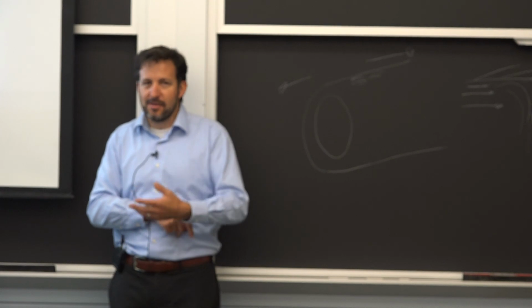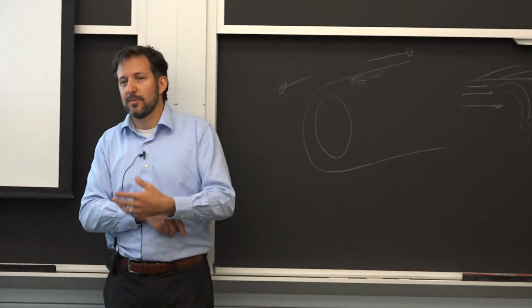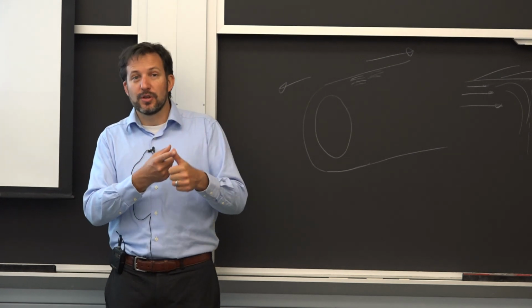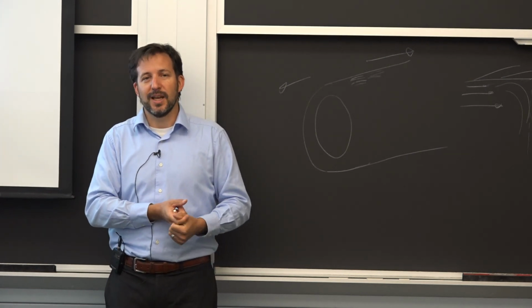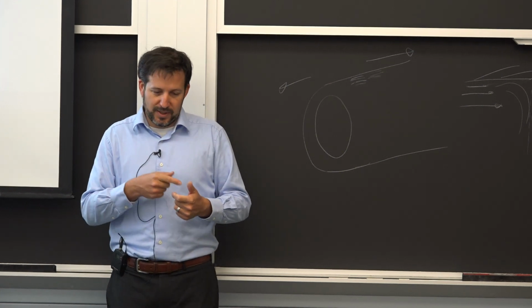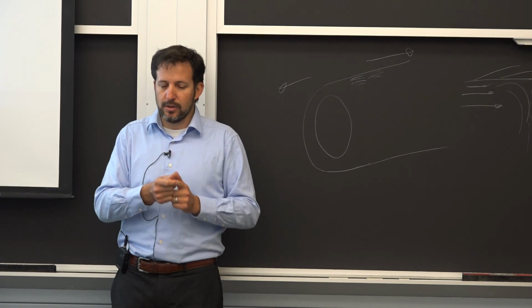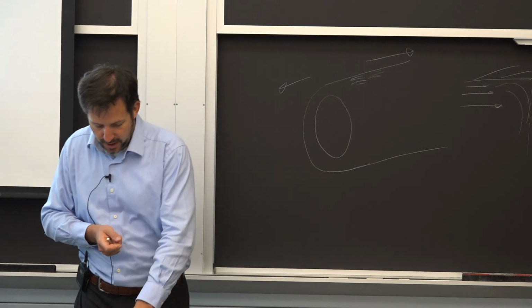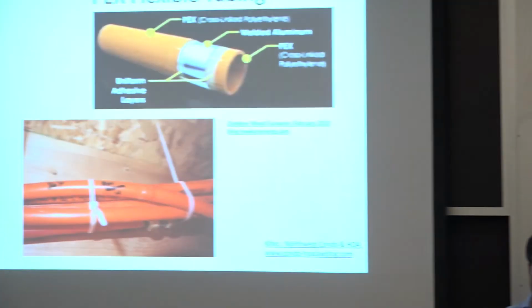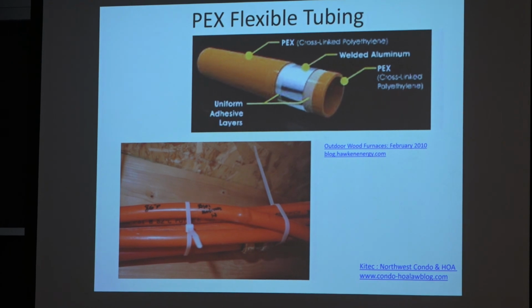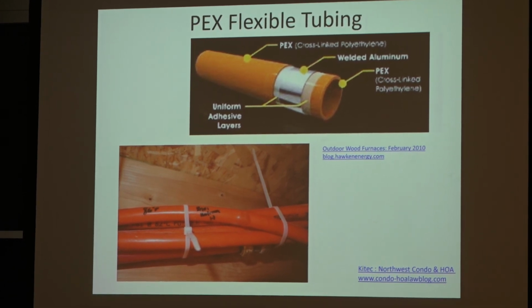after 10, 15, 20 years of using those pipes and understanding what happens, first of all, long term, that the strength's going to be going down by a factor of 20 to 50. And then is there going to be any interaction, in this case, with the water? And that's where I have another example here of very cool technology where you have plastic on the inside, you have a little aluminum layer, and then you have plastic on the outside. The purpose of the aluminum layer was to prevent oxygen from getting into the heating system, because that causes corrosion of the burner system and everything in there. So it's an oxygen barrier for going inside.